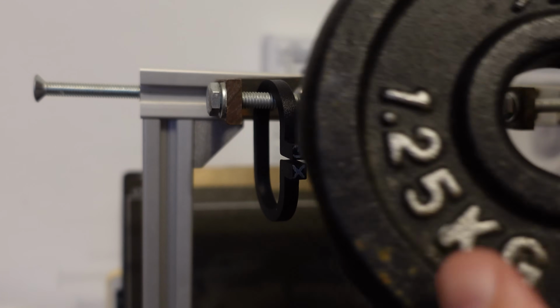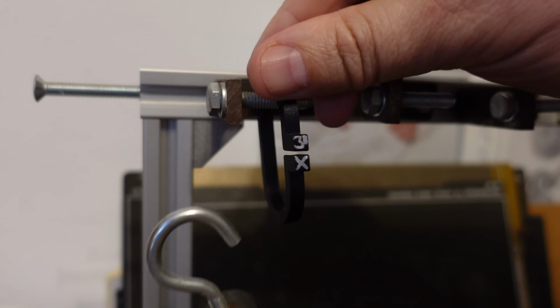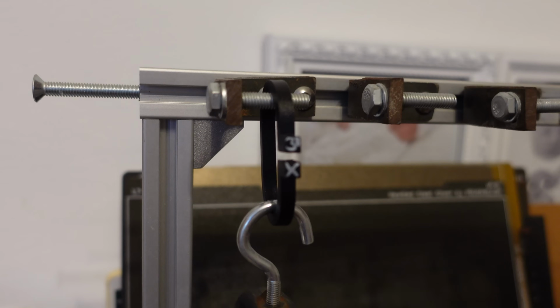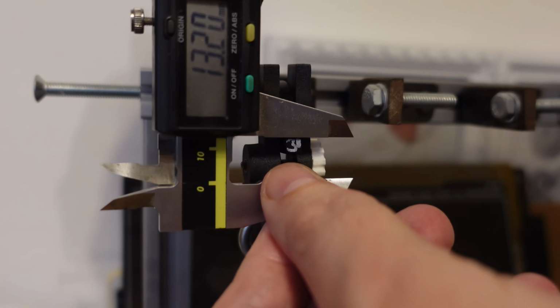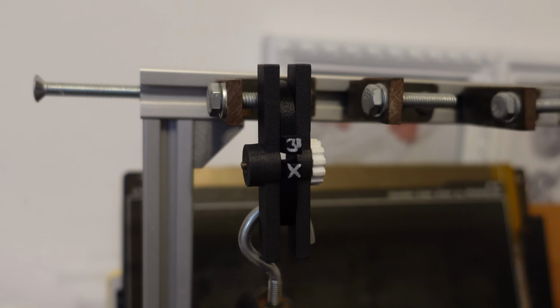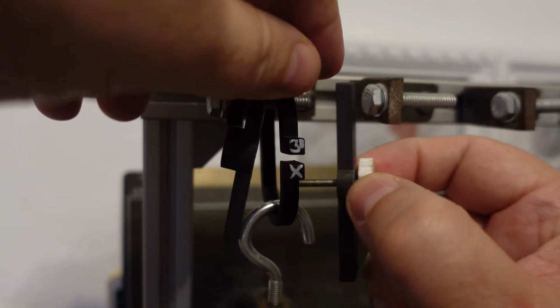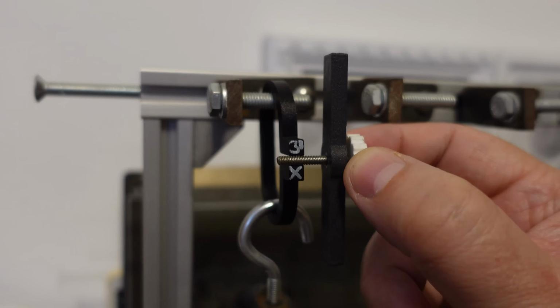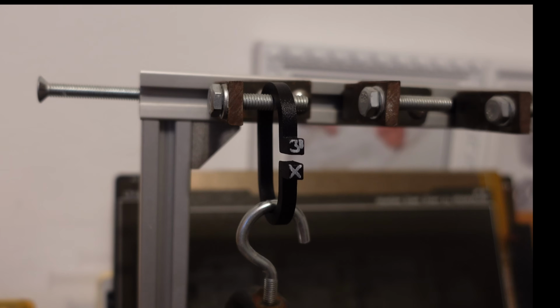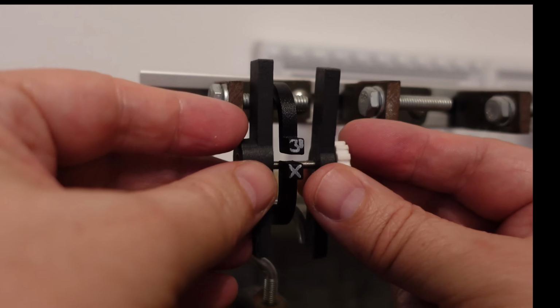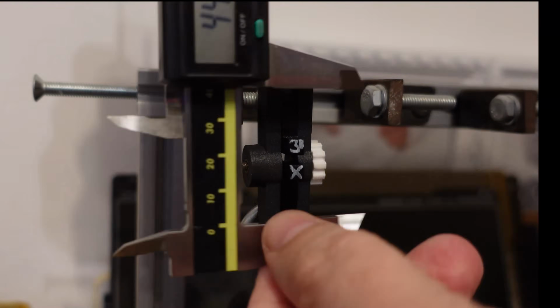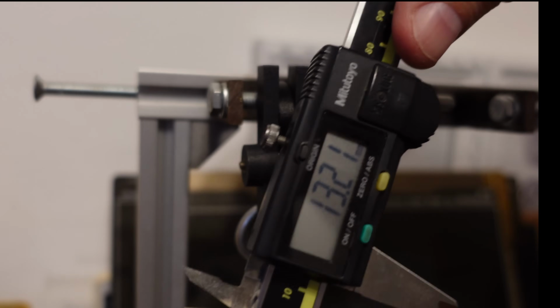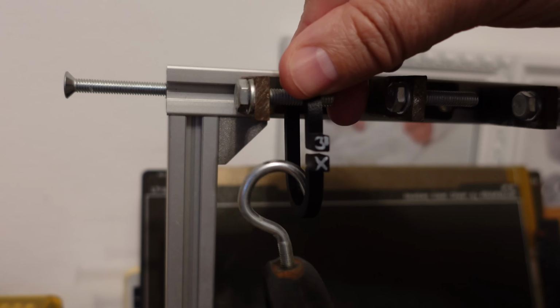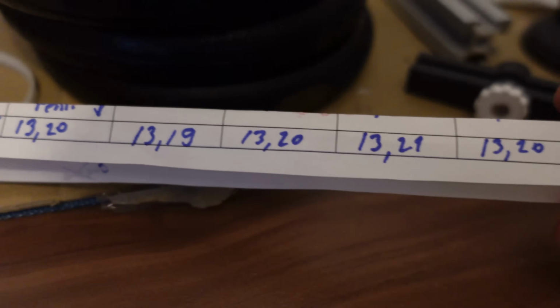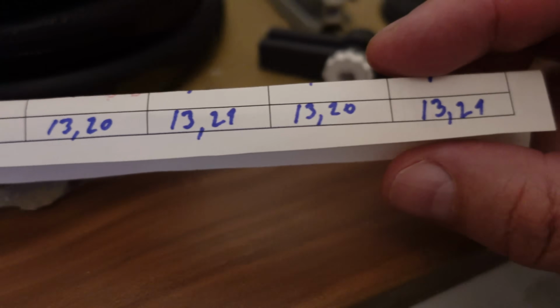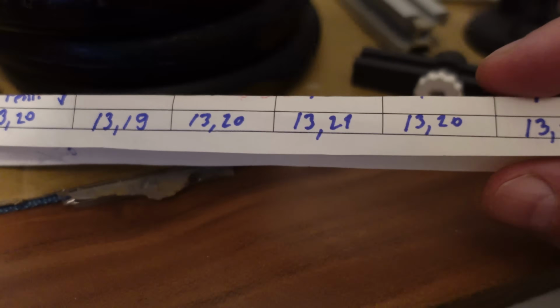Creep test, the deformation under a constant load of 1.25 kg. Very minimal deformation. 13.20. The deformation is so small that I have to go around. It cannot go through this gap. Day 5, the last measuring, and almost no deformation so far. 13.21. This small deviation is just a result of inaccuracy in the measuring, but basically absolutely no creeping of this material.